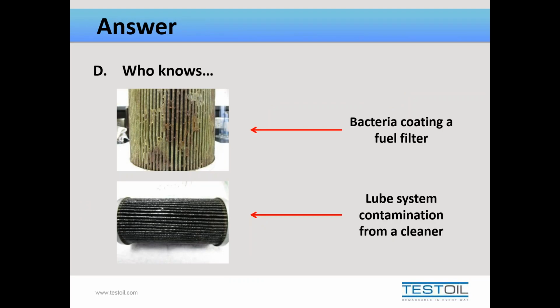On the top filter, we actually have a fuel filter, and that is bacteria that's actually coating the fuel filter. And on the bottom, we actually have a system that was due for a new charge of fluid, and during the cleaning process, the cleaner was not completely removed, and it actually reacted with the lubricant to form this brown sludge that was being caught by the filter.